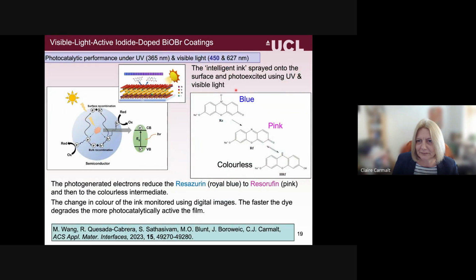While sticking on bismuth materials, we've also been very interested in these oxy halides. The reason behind that is because when you look at their structure, this is the sort of layered structure that they have. So you have layers of your sort of oxo-bismuth cation with your halide ions sandwiched in between. And that leads to internal electrical charges, which is thought to help reduce recombination between the electrons and the holes. So what's happening when you're interested in these as, for example, photocatalysts, you're obviously irradiating with UV or visible light, and your electron then is promoted from the valence band to the conduction band.